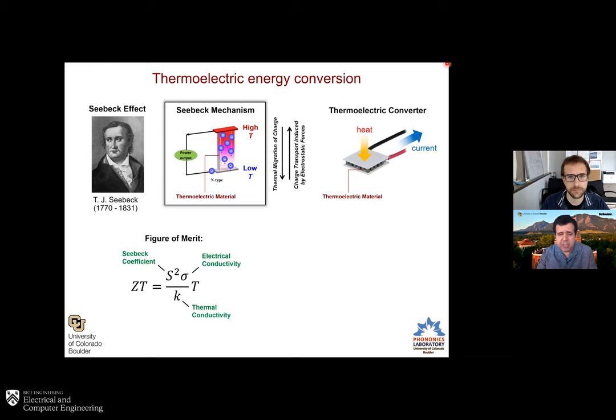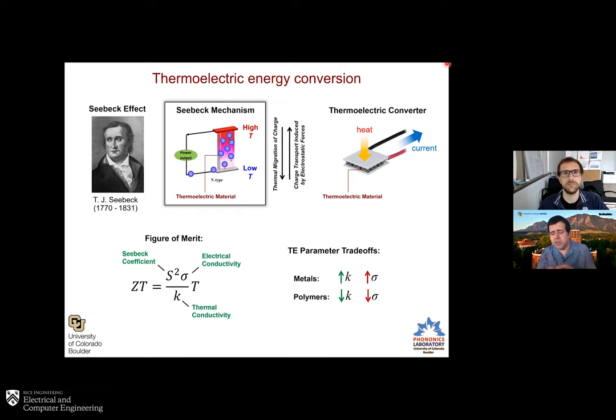So clearly, you can see here, and this has been one of the challenges of thermoelectrics, that transport properties tend to go together. For example, in metals, they're good conductors of heat and electricity. Polymers are the opposite. So it's really hard to uncouple those effects. And in fact, there's a phrase whereby it is said that the target is to get a material that behaves like a crystal when it comes to electrons, but behaves as a glass when it comes to phonons. So this has really been the challenge for improving this ZT figure of merit.